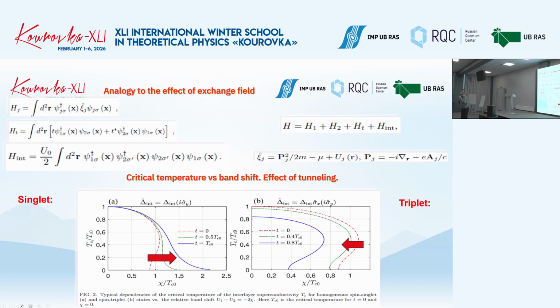We do not have now this spin splitting due to the exchange field. But we have a ferroelectric moment, which we suppose to be responsible for the shift of the bands of electrons in neighboring layers. The Hamiltonian is quite simple: it's kinetic energy, plus some tunneling between the films. This is important, and it is different from the simple picture which I told you before. For the analogy with ferromagnet-superconductor interaction, this tunneling effect should be a sort of spin-flip term. And this is the interaction for interlayer pairing, and these are the phase diagrams.